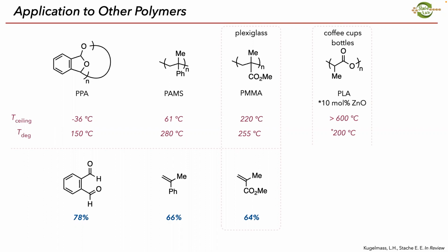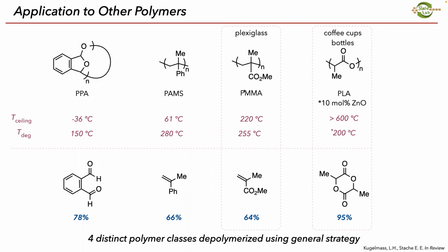We can use a co-catalyst. We add in a little bit of a Lewis acid, zinc oxide. Under our photothermal conditions, we get 95% of the monomer back, with 90% of it being L-lactide, which is what we use to polymerize to PLA. So this process is highly selective for forming the monomer, even though these are all 4 completely distinct polymers. We can use a single strategy, or we can use co-catalysis to depolymerize these.